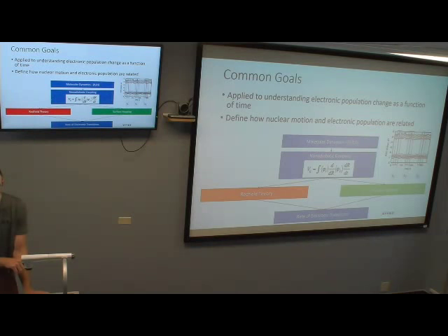It's just that you're going to have to put a lot more time into it, because depending on the time scale of the atomic motion you're interested in, that's how long your trajectory is going to have to be. Like those rotations with methylammonium, if they're on the scale of 2 to 5 picoseconds, you have to have a really long trajectory, versus running it for 100 to 150 femtoseconds and potentially having a good enough answer.